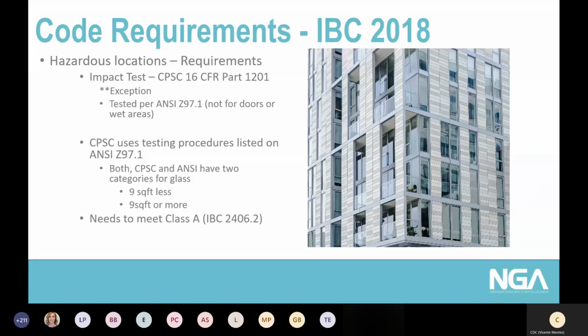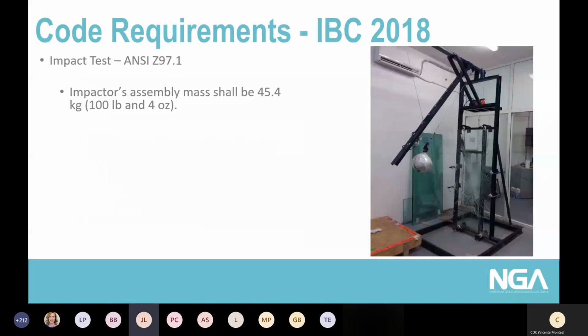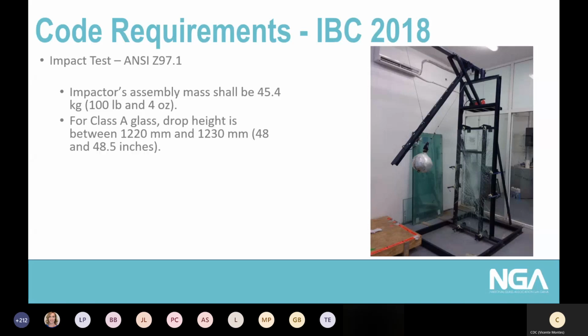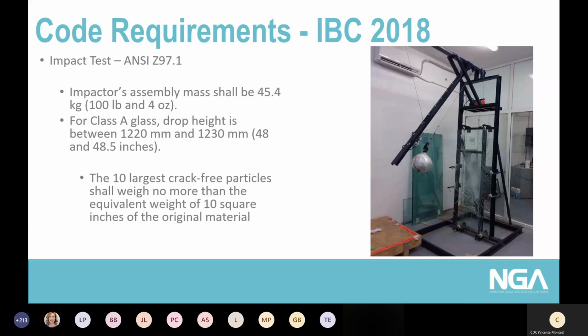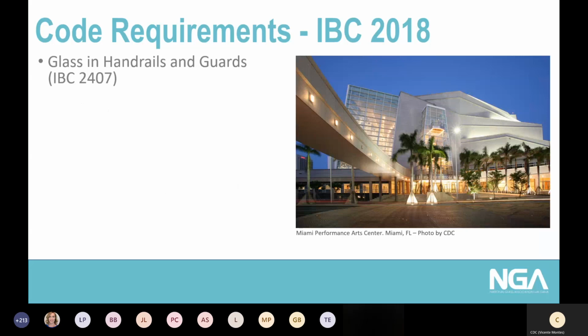Glass in railing applications needs to meet classification A, Class A. The impact test per ANSI Z97.1 looks something like this. You have an impactor assembly, and the mass of this impactor needs to be 100 pounds and 4 ounces, very specific. To meet Class A, your drop height needs to be between 48 and 48.5 inches, also very specific. The pass-fail criteria is that the 10 largest crack-free particles should weigh no more than the equivalent weight of 10 square inches of the original material.